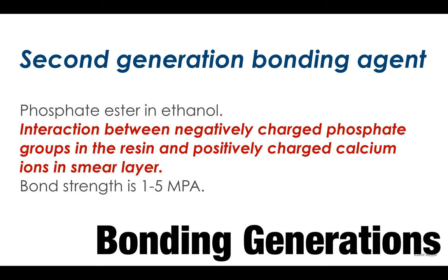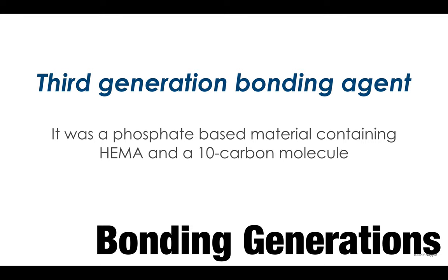between the smear layer, which is quite weakly attached to the tooth surface. And we know that this smear layer was being produced during the preparation of the tooth surface. And the bonding strength is, of course, because it is totally relying on the smear layer, no more than 1 to 5 megapascals. The third generation contained hydroxyethyl methacrylate, which is a hydrophilic monomer, and it was not good as well. Then comes another system, which was initially classified on the basis of steps.